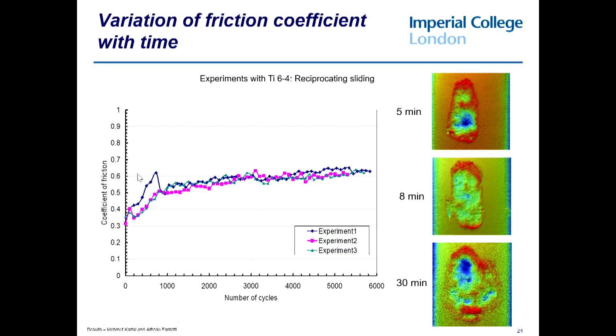What you find if you do those kind of loops is that the coefficient of friction increases quite dramatically to start with, and then perhaps a bit more slowly. Almost certainly what's going on is that you've got some kind of surface cleaning taking place to start with, and then you get a gradual degradation of the surface due to wear.